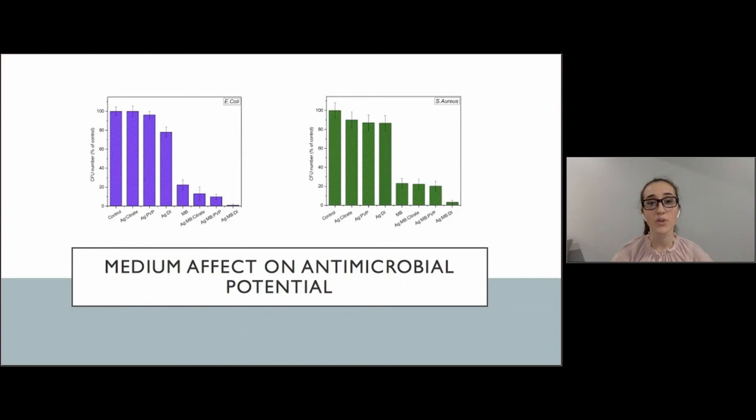The experiment was also conducted again to demonstrate the effect of the mediums that the silver nanoparticles were in on their antimicrobial effect. After 3 minutes of light irradiation, we found that the DI water was the most effective compared to PVP as well as the citrate solutions. This may be due to the fact that the silver ions are attracted to hydroxyl groups, which are present in water, and so this results in the release of more silver ions to attack the cell membrane of the bacteria.